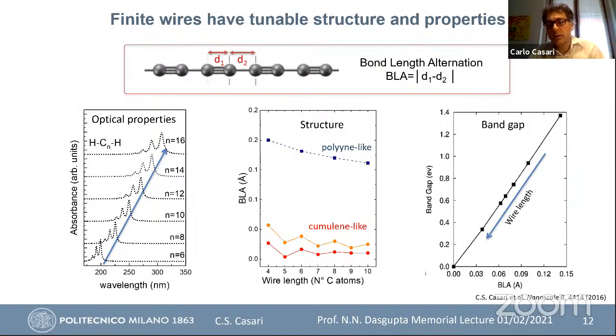Okay, now I just mentioned that the very long chain is no more affected by the size, because this is an important property in fact. So finite chains are actually very interesting, because the properties depend on the termination and the size. So the number of carbon atoms composing the wire and what kind of terminal atom or functional group you put at the end. So for example, here you can see from theoretical predictions what is expected to happen to optical properties by changing the number of carbon atoms of a carbon atom wire terminated by hydrogen atoms at the ends. And so you see a very nice shift of the optical absorption towards the visible for increasing the length of the carbon atoms.